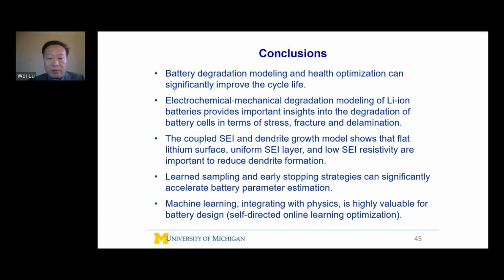And at the same time, we can develop better technology to reduce SEI formation, therefore improve the battery cycle life. Now, the other important factors will be the loss of active material, such as on the anode side or cathode side. So they will also contribute significantly to battery degradation. And in terms of other mechanisms, such as manganese dissolution, transition metal dissolution, and other factors, they will also contribute to the degradation, especially in the later stage.